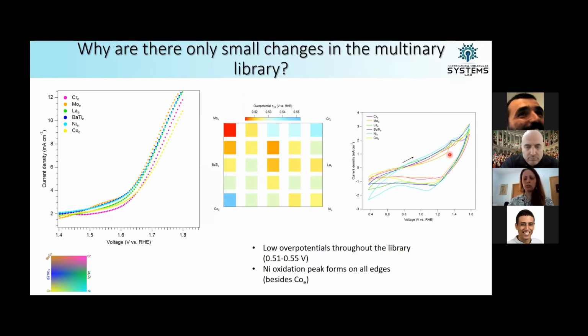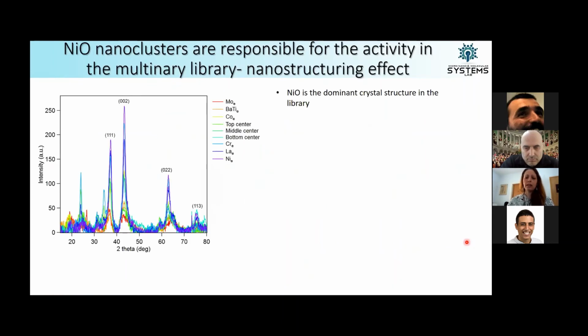So either nickel +2 to nickel +3 or nickel +3 to nickel +4, which we both have based on XPS measurements in our library. And indeed, if we then look into XRD measurements, what we're able to actually see, and these are XRD measurements over 9 points within the library, is that throughout the library, every single point shows nickel oxide as the dominant crystal structure. Some show additional crystal structures, which we haven't figured out yet, but all of the points show nickel oxide.